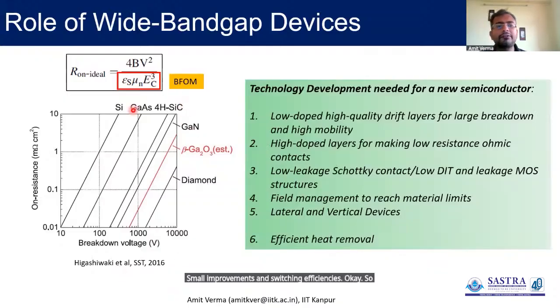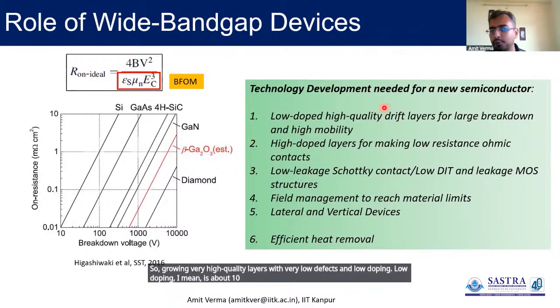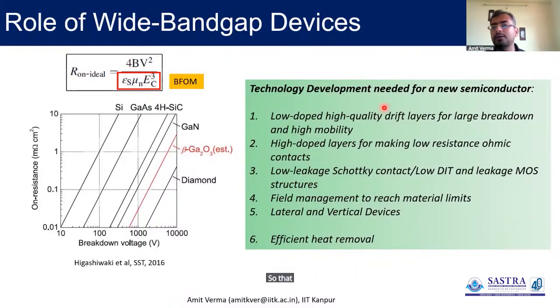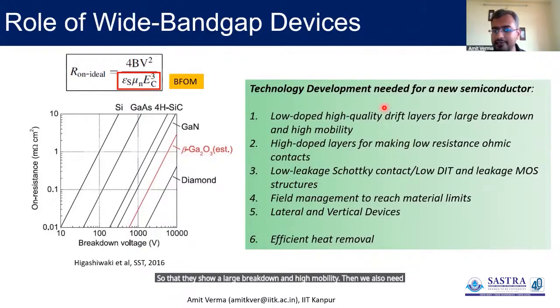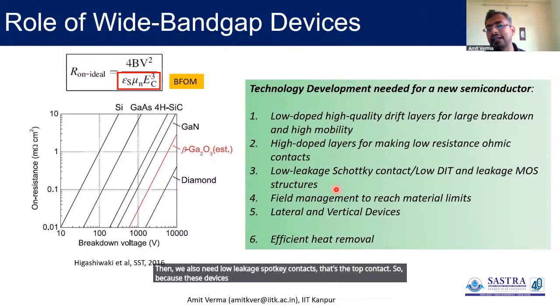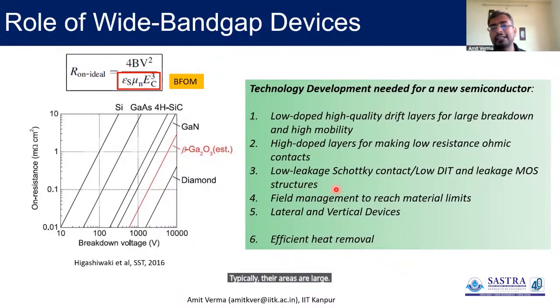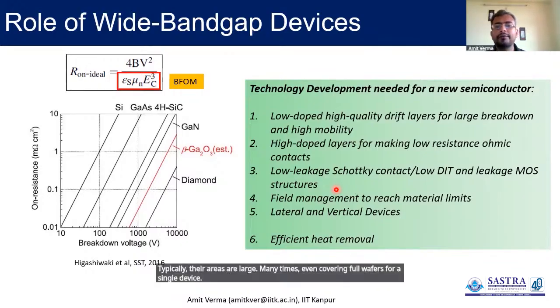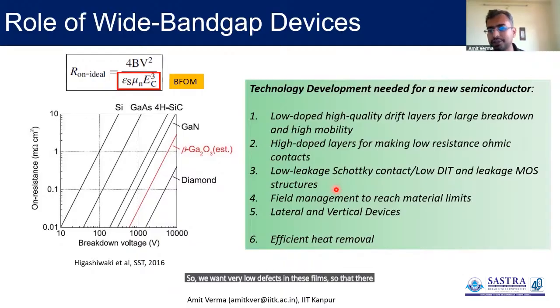So if you want to develop any of these technologies, what are the critical sub-technologies? One is low doped, high quality drift layers. So the drift layer, the top layer I was showing. So growing very high quality layers with very low defects and low doping. By low doping, I mean about 10^15 per cubic centimeter, 10^16 per cubic centimeter or so, so that they show large breakdown and high mobility. Then we also need highly doped layers, like the bottom one, to make good low resistance ohmic contacts so that on-resistance remains low. Then we also need low leakage Schottky contacts, that is the top contact. Because these devices have to carry large currents, typically their areas are large, many times even covering full wafers for a single device. So we want very low defects in these films so that there is low leakage through the Schottky contact, or there are some MOS structures also. So we want low leakage in them.